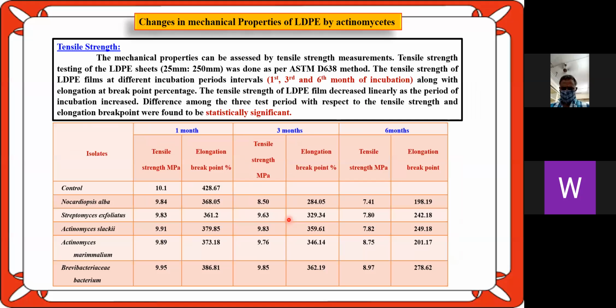Changes in mechanical properties of LDPE. The tensile strength of LDPE films at different incubation periods, 1, 3, and 6 months, along with elongation breakpoint percentage. The tensile strength of LDPE film decreased linearly as the period of incubation increased. So you can see the control possessing 10.1 megapascals with elongation breakpoint 428.6, whereas Nocardiopsis alba and Streptomyces exfoliatus have decreased from 9.8 to 7.4 after 6 months and 9.8 to 7.8 after 6 months, followed by slacki, mammalium, and Brevibacteriaceae bacterium.